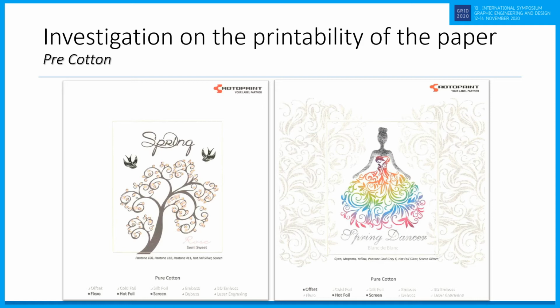The absorbency of this paper combined with the porosity is so great that highly pigmented inks such as silver and gold bronze are almost absorbed in depth and are poorly reproduced. This paper has an exceptional, pleasant-to-touch texture, which is evident from the measurement of its smoothness. This quality makes it suitable for wine labels with clean designs.